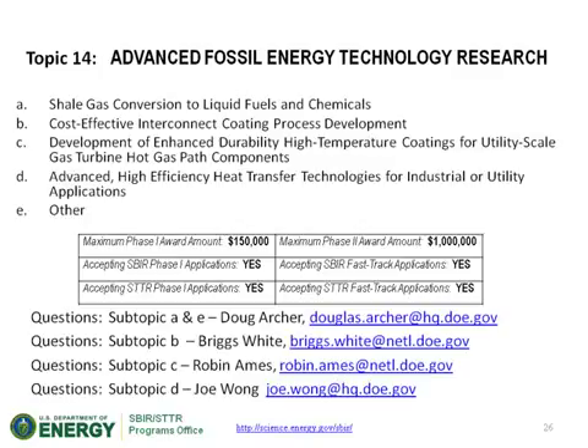And so that research also showed that when interfaced with yttria-stabilized zirconia coatings, the seals didn't degrade. However, after doing some investigation with some of our partners within the program, we found that there really wasn't a commercially available process for depositing yttria-stabilized zirconia coatings onto stainless steel interconnects to protect those seal areas. So we're looking for some kind of a process that could cost-effectively put down that coating and do it in a thin, continuous coating, and that could ultimately be scaled up for mass manufacturing.